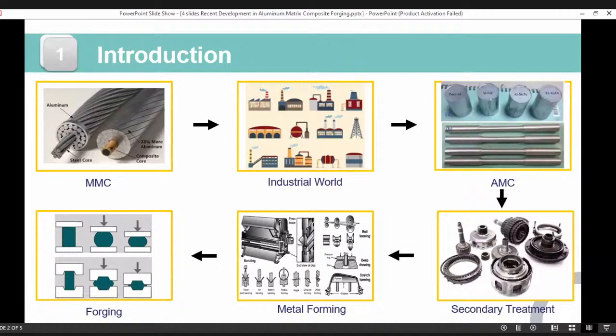Metal matrix composites have become one of the most widely used materials for industry. One type of metal matrix composite is aluminum matrix composite. The method commonly used to produce AMC is stir casting, but the conventional method generally has several problems like porosity and non-homogeneous particle distribution. This problem can be solved by secondary treatment, like the forging process. The advantages of the forging process are superior mechanical properties, favorable grain orientation, no material waste, etc.